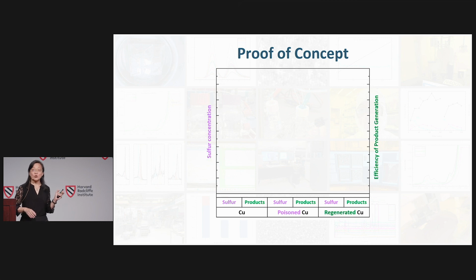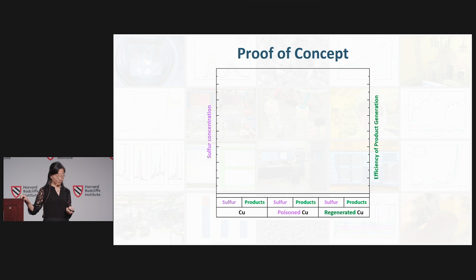The first y-axis shown on the left is in purple. That shows the concentration of sulfur. The second y-axis on the right is shown in green. That is the efficiency of the product that we generate. And I have 3 sets of data. Each of them carries 2 sets of information, sulfur concentration and efficiency of product generation. I have, on the bottom, clean copper, poisoned copper, and regenerated copper after we treat it with the atomic layer etch process. Okay, let's look at the sulfur concentration first.